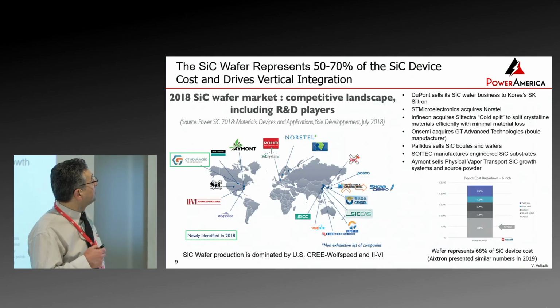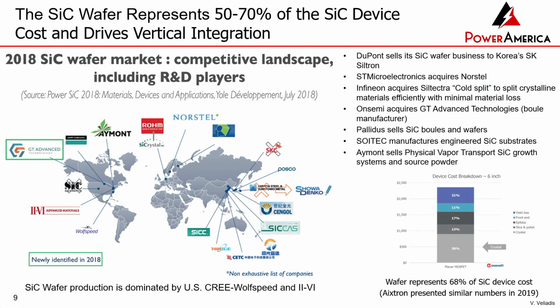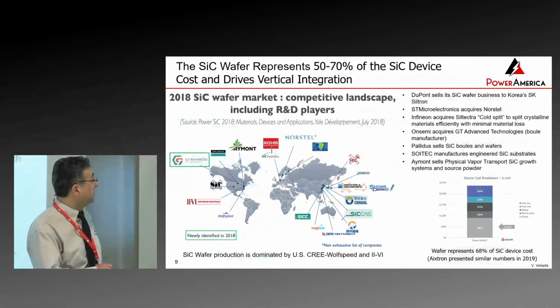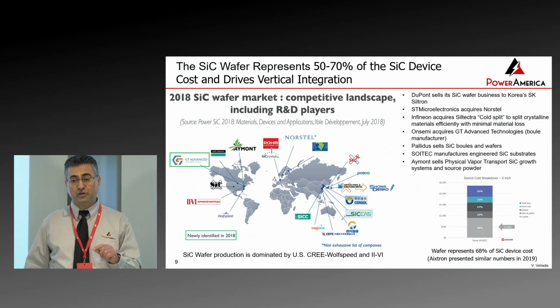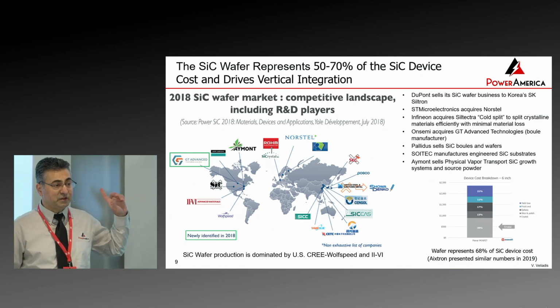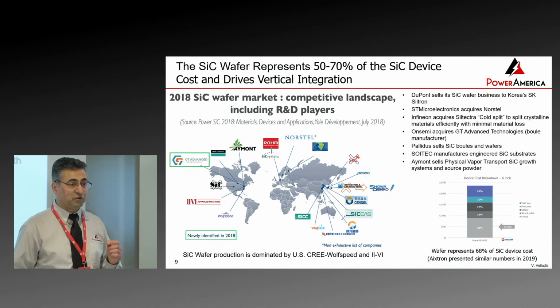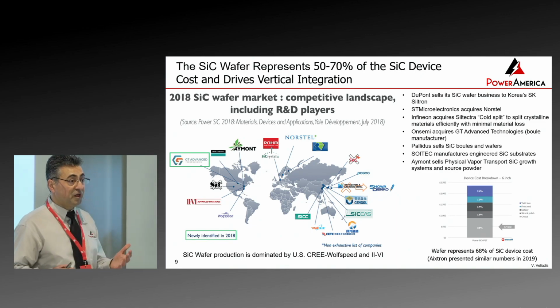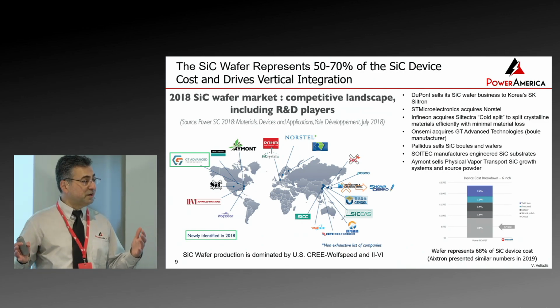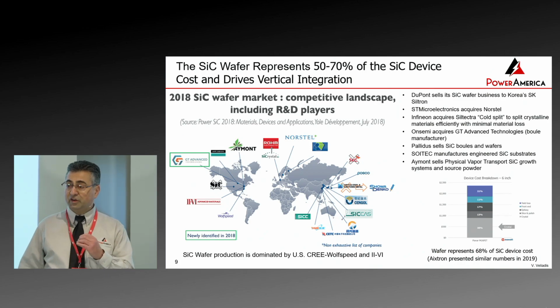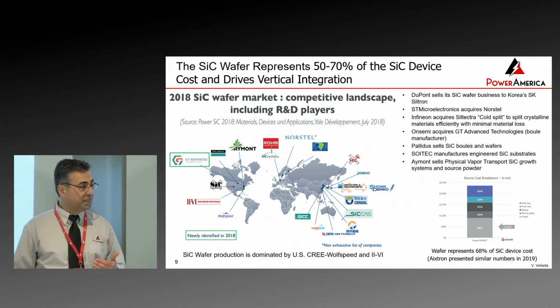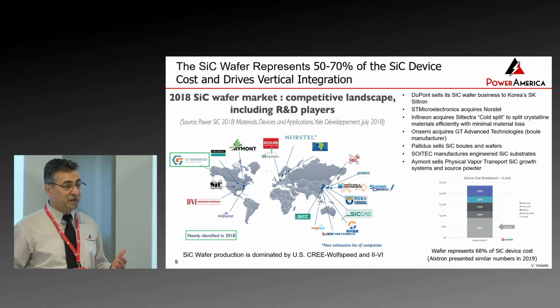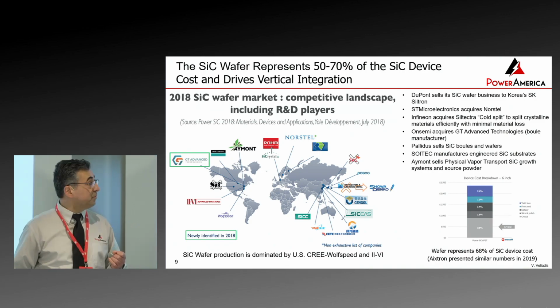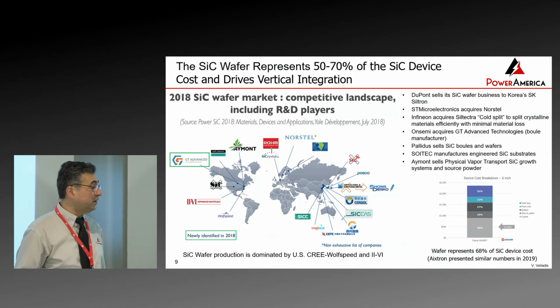So what does all this come down to? It comes down to the fact that the silicon carbide wafer represents about 50 to 70% of the silicon carbide device cost, depending, of course, on who you ask. And that's a very big amount of money to pay for the substrate itself. And this is really what's driving the vertical integration that we're seeing today. Any company that knows how to make a substrate, because the learning curve is a very, very steep one for the substrate, any company that knows how to make a silicon carbide substrate is pretty much sitting on gold. And some of the examples, if you look at GT Advanced Technologies, right, they were making ovens, they were selling ovens for silicon carbide boules. Well, they realized that selling the oven with a recipe is actually very, very valuable. The recipe itself is very, very valuable. So what they did is they became a producer of volume, and as expected, onsemi wanted to have an internal supply of silicon carbide to reduce this margin, to drop it maybe from 50 to 70 to around 40, so they were bought.